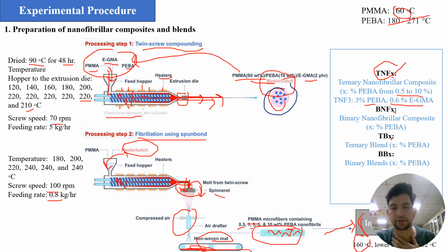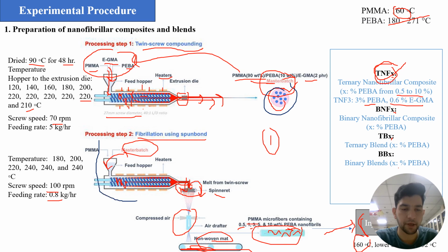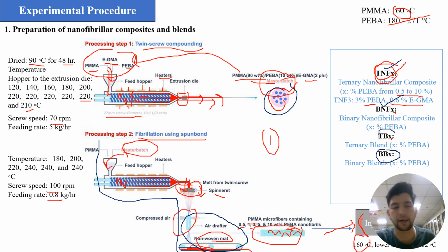Okay, here a question arises: how did he make these? First of all, he made the master batch, and in the second step, when he wanted to make nanofibers, he started the experiment from here to here and made nanofibers. So TNF contains fibers, BNF contains fibers, so he did the whole procedure. But for TBX and BBX, which have no fibers, he started the experiment from here, did up to step 8, and from here he collected the sample. So he combined PMMA with PEBA and stopped here.